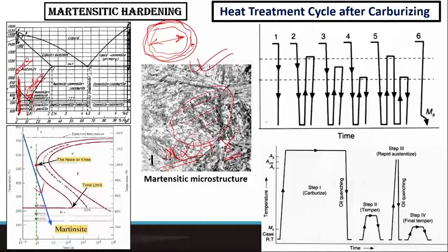In solid state, with liquid, in contact with a liquid bath or a molten salt bath, or in contact with a gaseous environment, or gaseous environment backfilled after creation of vacuum. In all these cases, the surface is exposed to a highly enriched or carbon enriched environment, and that's where carbon comes in. So that process requires diffusion, and that's why we have to maintain high temperature.